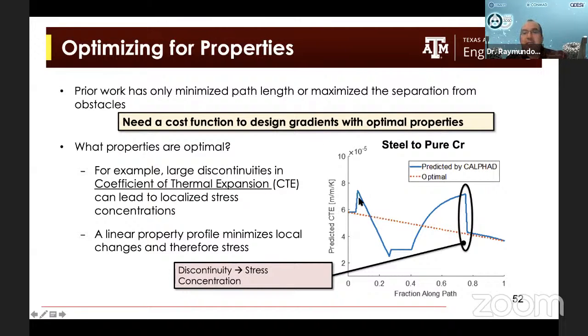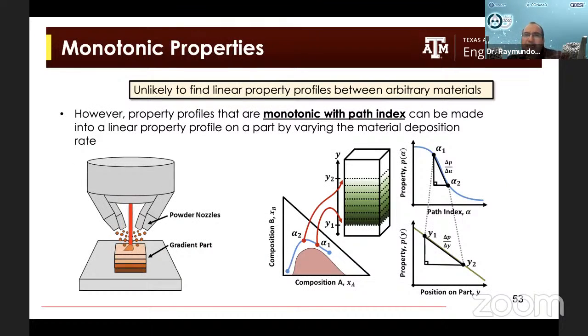For example, if you plot the thermal expansion coefficient of this path going from steel to pure chromium, it turns out that the thermal expansion coefficient changes by a lot as you move in the path, and changes in thermal expansion coefficient and discontinuities in the thermal expansion coefficient can lead to thermal stress concentrations, and that can compromise the integrity of the part. So the question was, can we actually do something to try to minimize these drastic changes in properties while at the same time avoiding detrimental obstacles? So essentially what we wanted to do is to try to find ways of printing a path that avoided obstacles, but also that ensure that properties change monotonic.